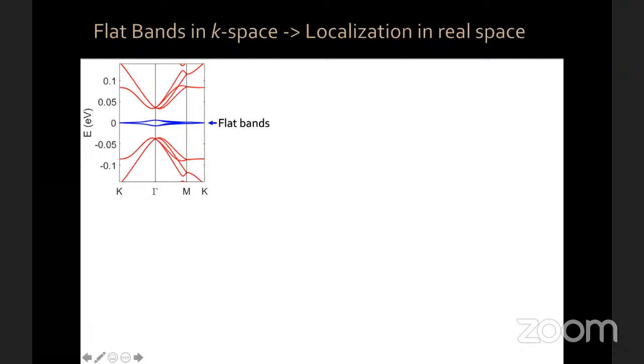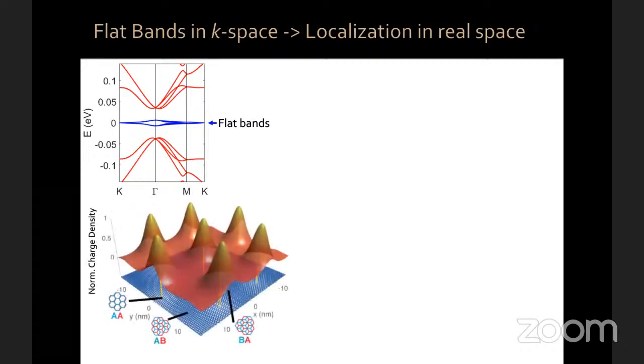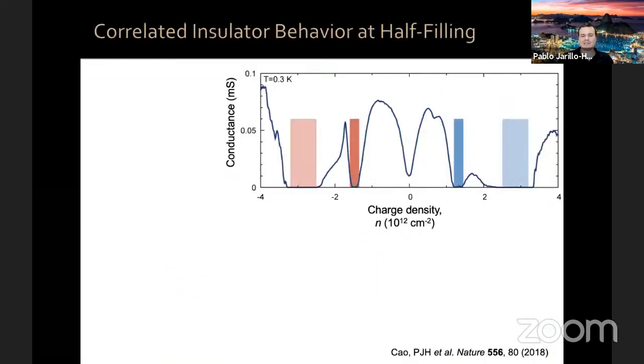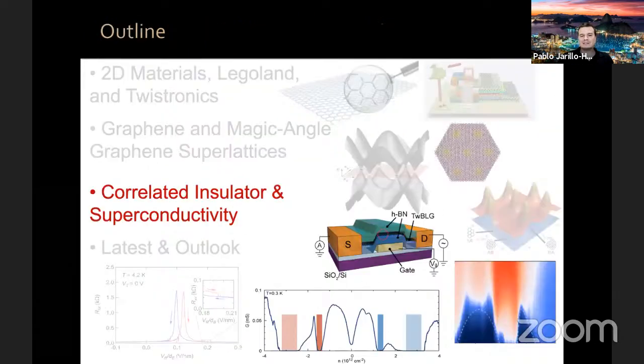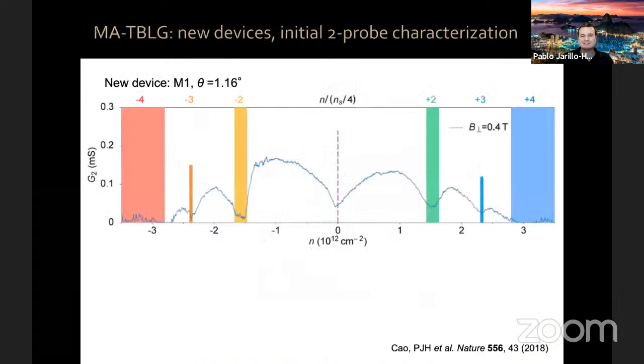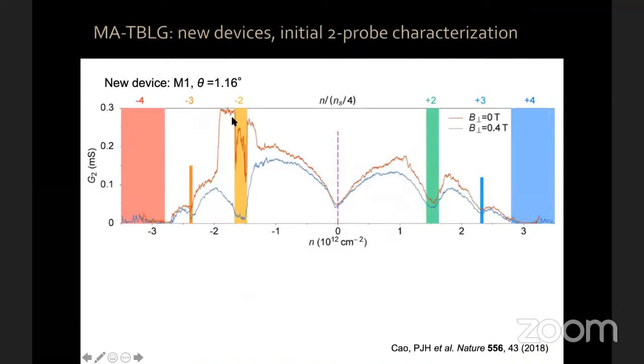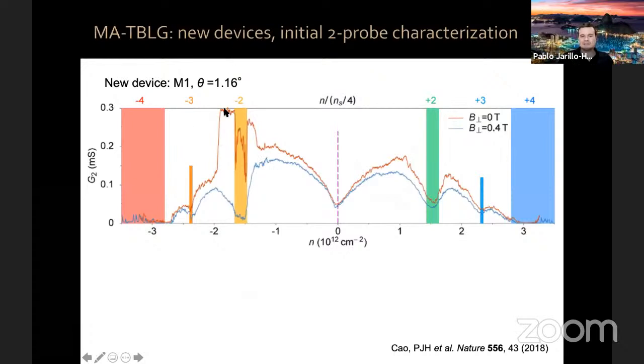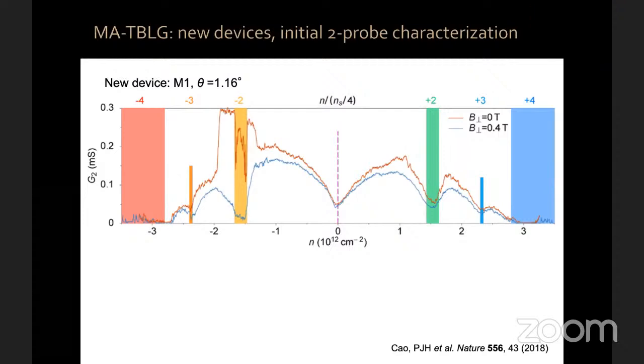And it seems that there is a tendency for the magnetic field to try to recover the symmetry when you show a plot with zero magnetic field and one with 0.4 Tesla. It was not so much. What happens is that the effect of superconductivity in this plot is very dramatic, because superconductivity sends the two-terminal conductance to infinity, and that's why it looks like a dramatic effect here. It is dramatic because you're a superconductor, but it's not so much that it restores the symmetry. What the magnetic field does is it kills superconductivity. I see. And a last question.